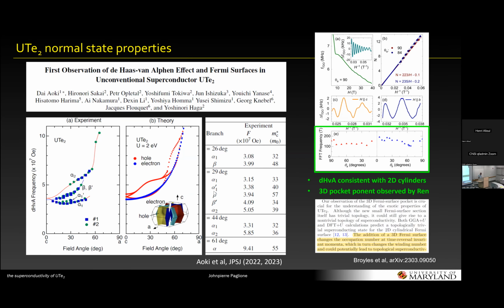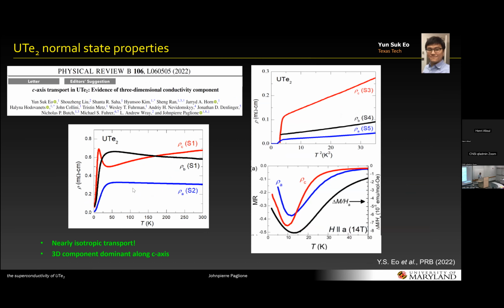And then, to make it even worse, you might think this quasi-2D band structure results in quasi-2D transport or anisotropy. But in fact, we measured the transport anisotropy and it's fairly 3D. In fact, the C-axis resistivity is the same magnitude as B. There's a factor of 2 between A and B. B and C are about the same. But you can see right away this red curve shows quite different temperature dependence, with this peak at lower temperature than A and B. So there's something unusual going on here.